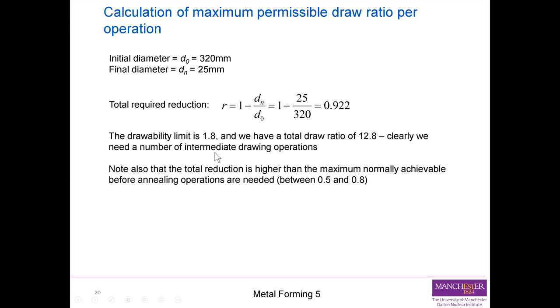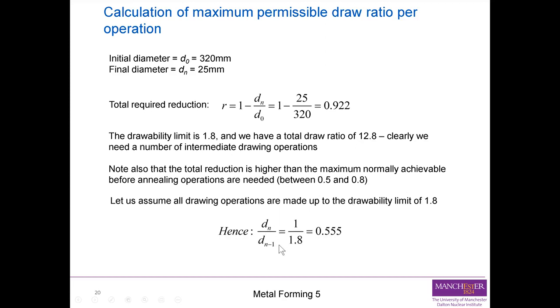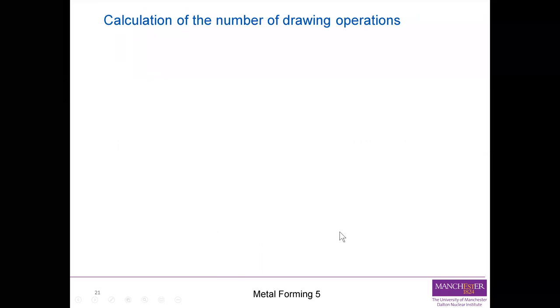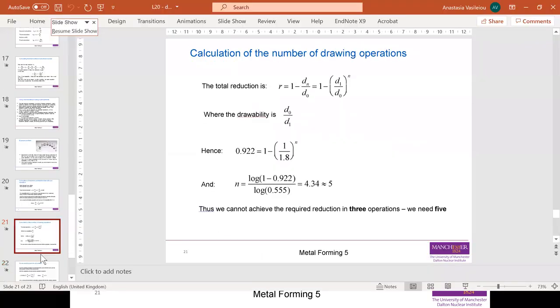So clearly we need a number of intermediate operations, because we exceed the limit. Note that the total reduction is higher than the maximum normally achievable before annealing, which should be between 0.5 and 0.8. So, as I said before, it's a good assumption that all drawing operations are made up to the drawability limit of 1.8, taking the process to its limits. That would give us Dn over Dn minus 1 equal to 1 over 1.8, which equals 0.555.